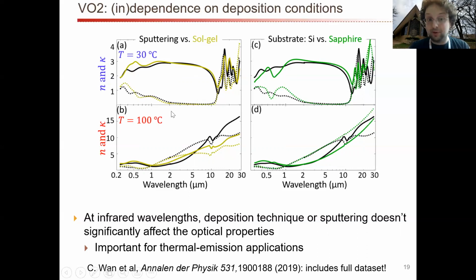However, there's this magic region between about 2 microns and about 11 microns, where pretty much every film is more or less the same, at least in the insulating phase, where these materials are also quite low loss and quite transparent. And so in this kind of magic mid-infrared range between about 2 and 11 microns, you can pretty much trust that no matter how you deposit your VO2, as long as it's reasonable quality VO2, like the stoichiometry is okay, it's at least somewhat polycrystalline, you are kind of expecting the optical properties to remain the same, and therefore you can actually use this full data set to do your optical design and trust that it's going to represent reality reasonably well. So we're quite excited about that finding.